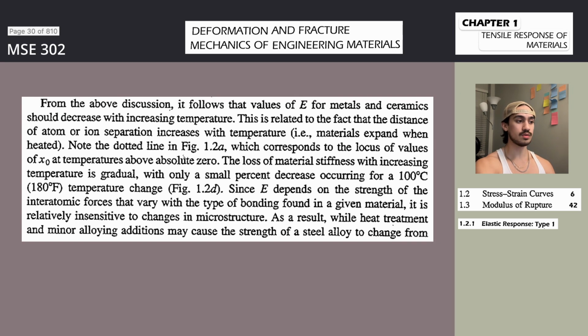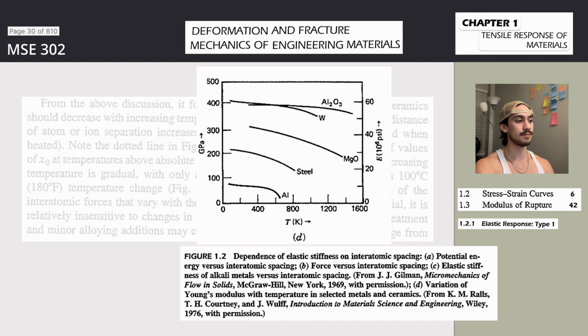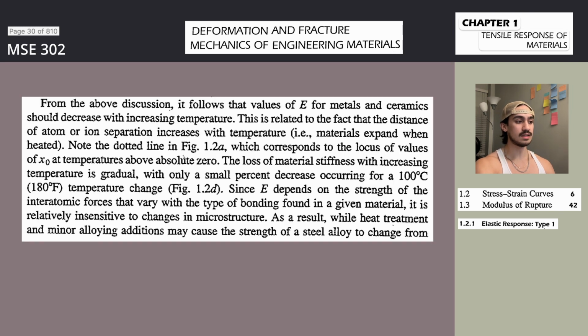Example, note that E111 is greater than E110, which is greater than E100, and that E110 is in good agreement with the average value of E, the Young's modulus of elasticity, for the polycrystalline sample, table 1-1.